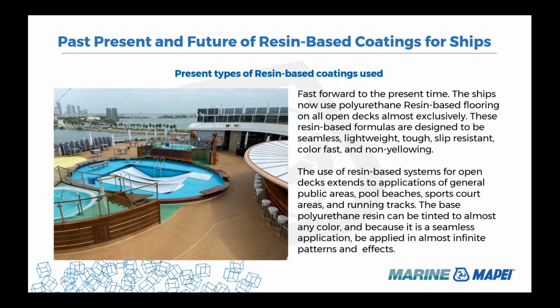The difference now is that the finishing of the decks with the resin-based flooring has changed. The areas where the synthetic teak effect decking was applied, we sand the surface with a very coarse sandpaper to give it a very coarse texture that approximates a wood grain. This also adds traction in those areas. And we also make end cuts or cross cuts across what we would see as the planks to give it more of a plank look, like you would see in a real wooden deck application. The other areas where you see the colored effects are typically sanded to a smooth finish, and that allows for a very nice looking and very easy to clean surface.